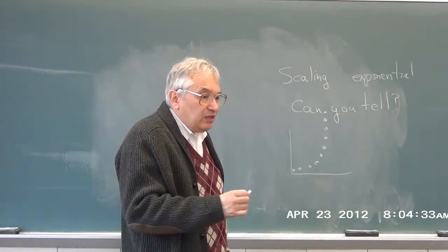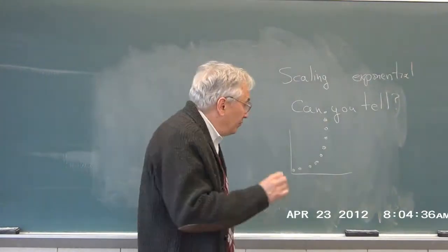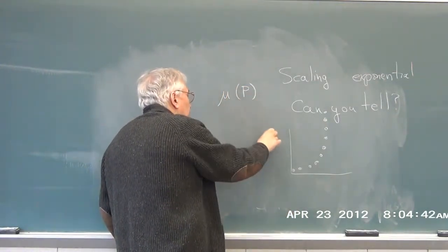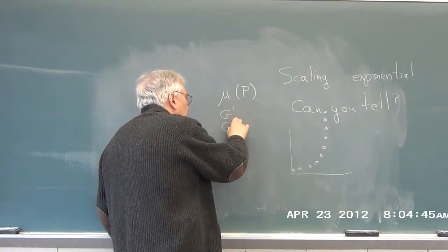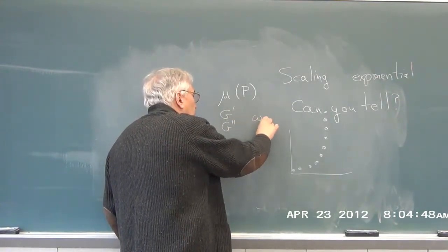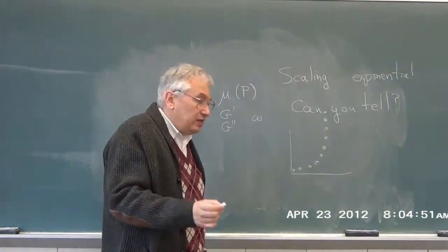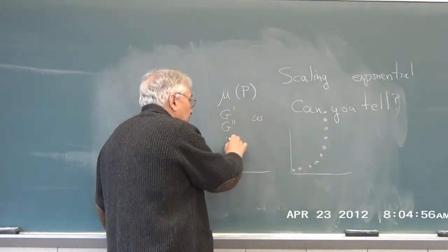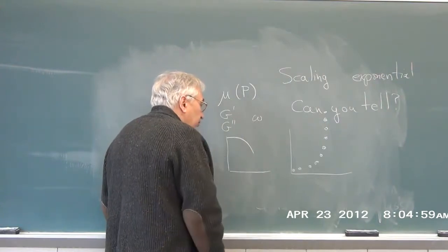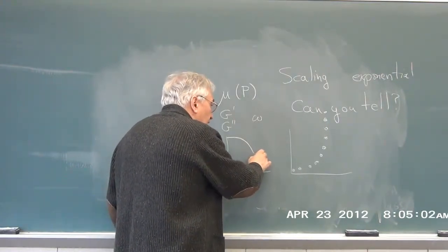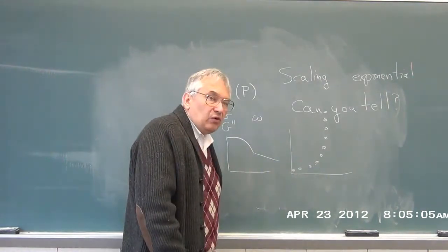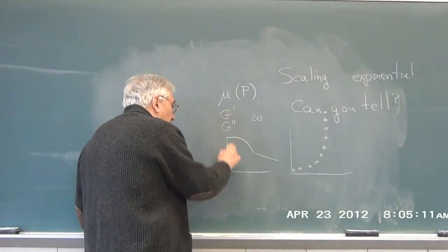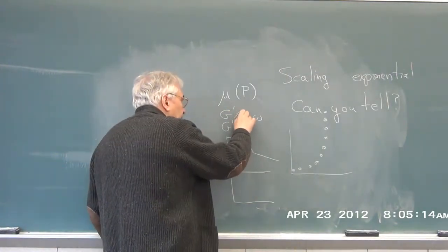And the answer is clarified by several sets of measurements that we've talked about already. For example, the electrophoretic mobility as a function of probe size, and the storage and loss moduli, which are functions of frequency. In both of these cases, using the same set of measurements on the same plot, we had a stretched exponential region, which was very clearly stretched exponential. And we had a power law region, which was pretty clearly power law, though the variation vertically there was a bit smaller. And for the moduli, as normalized,